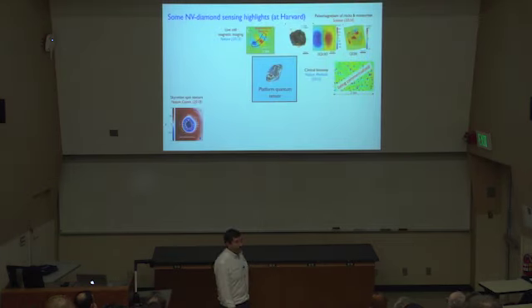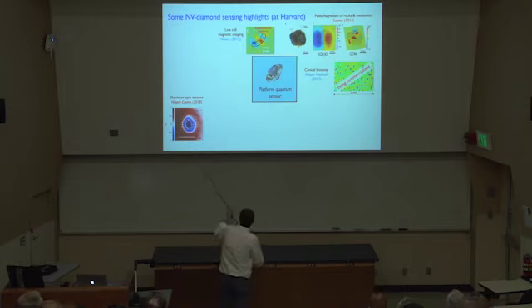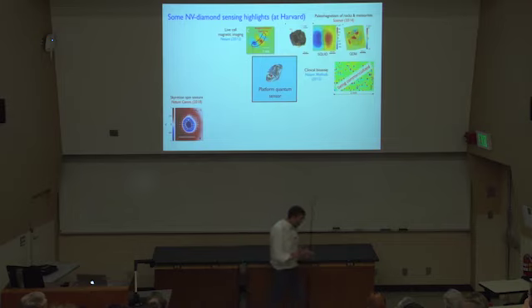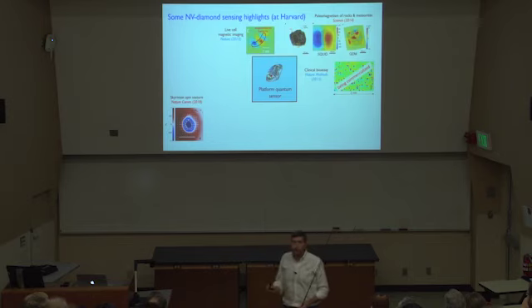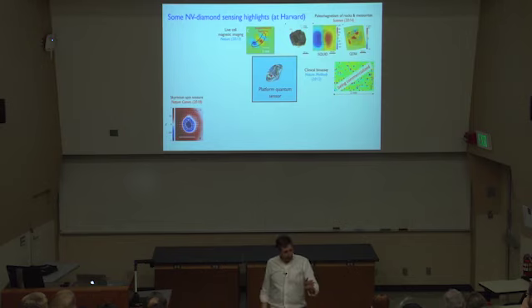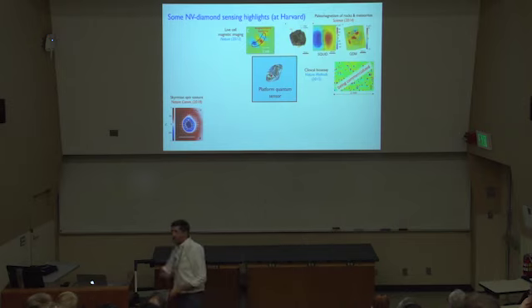Okay. Another field in which this technology is being very widely applied by many groups around the world now is in basic condensed matter physics. Working with my colleagues Amir Yacoby and Philip Kim, for example, we were able, in a paper published recently, to map the magnetic field pattern inside of magnetic insulator multi-layer systems in which you will find chiral structures related to what are called skyrmions, and determine that this is a particular Néel pattern rather than another kind of pattern of skyrmion, and in fact, the chirality of the skyrmion varies and changes as a function of height through the material. There are lots of other applications.